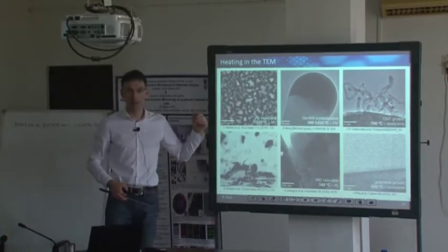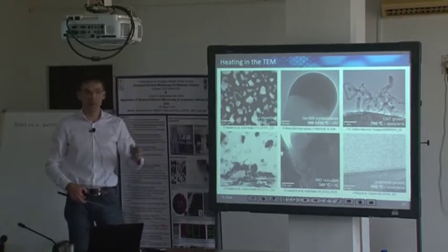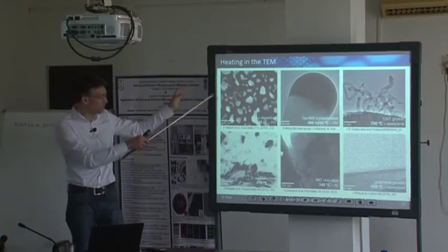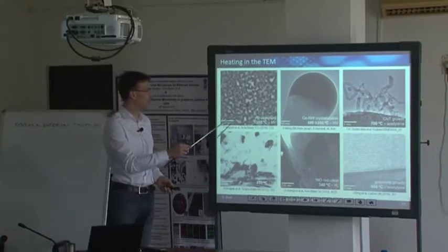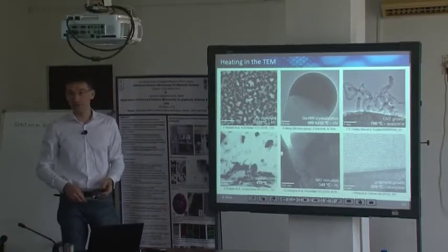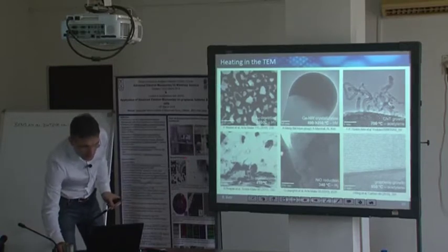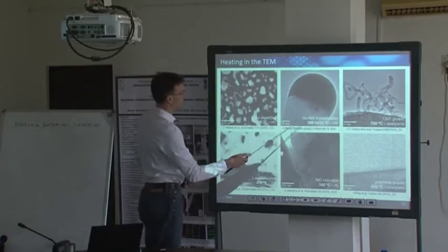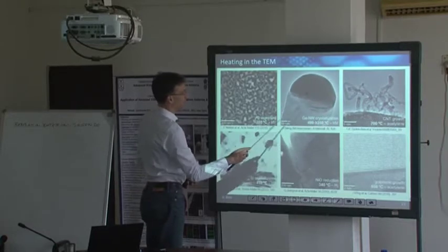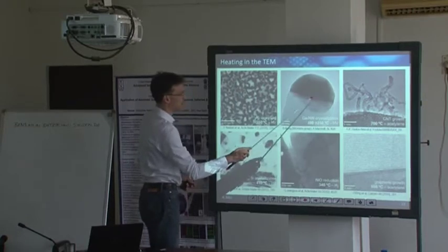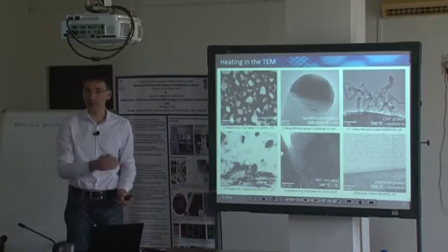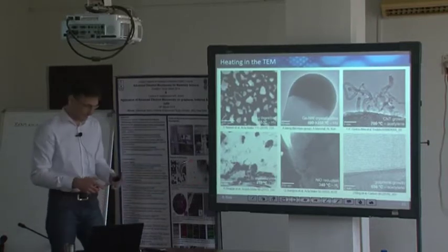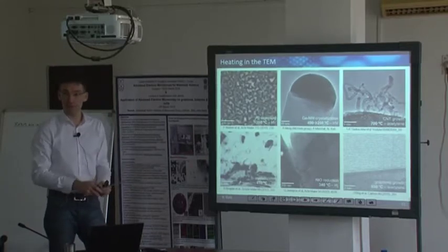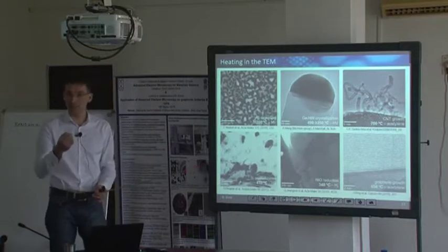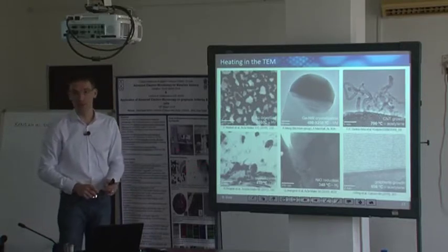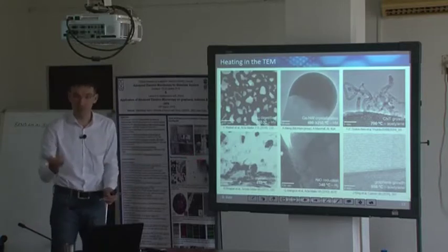And here, the question was whether the material, the gold, is transported via surface diffusion, via interface diffusion, or, I mean, there are many ways to redistribute the metal, and this all depends on what's going on during this process. This is just the recrystallization here in high vacuum at different temperatures of this uppermost tip. So this is liquid here, now it crystallizes, and in principle that occurs atomic layer by atomic layer if you look carefully. So structure formation is not that something just goes on in the bulk and it recrystallizes, but commonly it nucleates at some point, and then atomic layer by atomic layer the material crystallizes. So this is, for instance, a transformation of an amorphous phase to a crystalline phase.